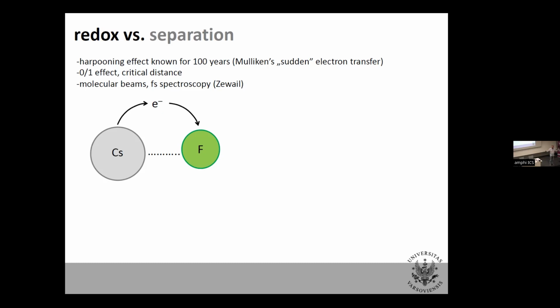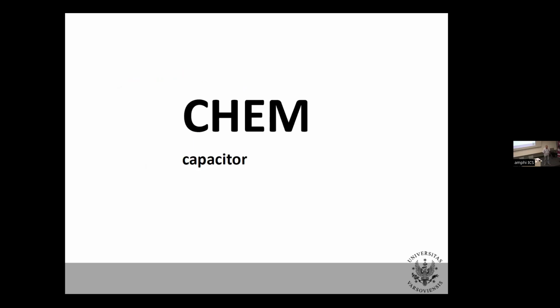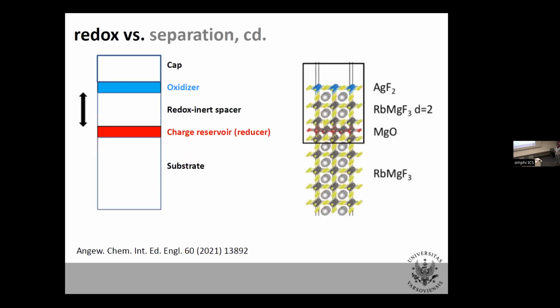So if atoms are more than 3 nanometers away, nothing will happen. But if they are closer than 3, there will be a sudden electron jump, the so-called harpooning effect, which is really well known for 100 years. It's just not put into the textbooks for some reason. So the message from this is that redox reactions, in fact, have a distance dependence, which is normally forgotten. And that distance dependence is relatively trivial, so that at large separation, there is no reaction, although this can be an immensely reactive thing. But at a certain separation and below, there is the reaction. So it's a 0-1 effect. Okay, now I pass to the core, with that introduction, to what I call chemical capacitor.